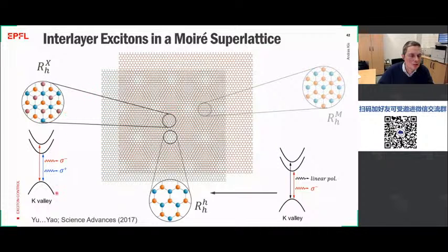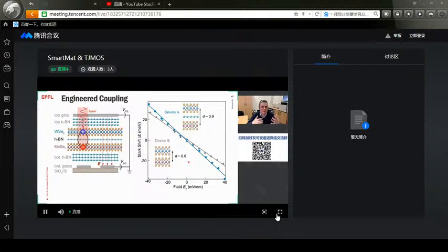So one region is going to emit with what we see, which corresponds to the interlayer separation. Again, if you put boron nitride in between, we get a larger size of the dipole, which is consistent, and it tells us that we indeed have here a single layer of boron nitride.